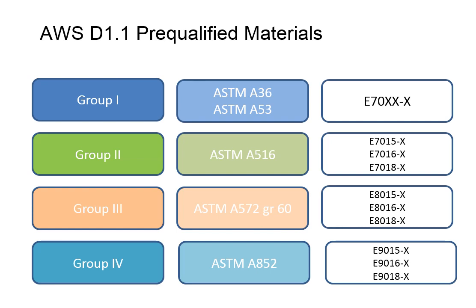And you look over here, I've got 3 columns here. I've got the groups, and then the second column is materials, a material I pulled off their list. And then the third row over there, the ones that are just outlined, the E70 XXX, that's a filler material. So you can see we can use anything there. We don't have to use low hydrogen. We can weld it with that stuff, and it's not an issue. So we could pick E7010, and we could weld with it, and there's no problems.